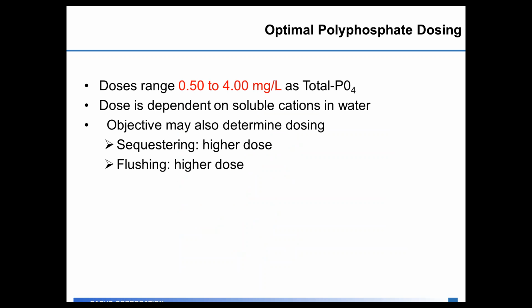When we talk about polyphosphate dosing, the dosage can have quite a large range, anywhere from a half a part to 4 milligrams per liter as total phosphate. The dose for your product is really going to depend on what you have to sequester in the water. If you have a lot of iron and manganese in the groundwater to sequester, you'll be on the higher side of that dosage. If you have lower levels, your dosage will be on the lower level.